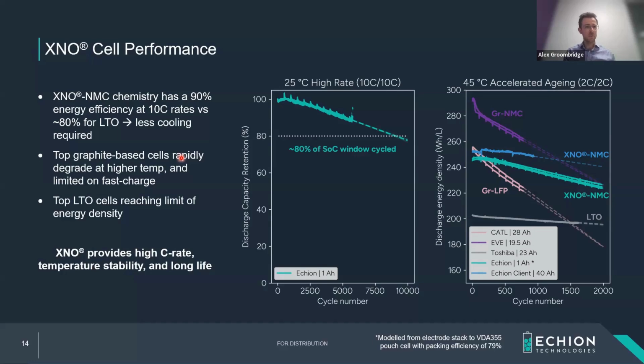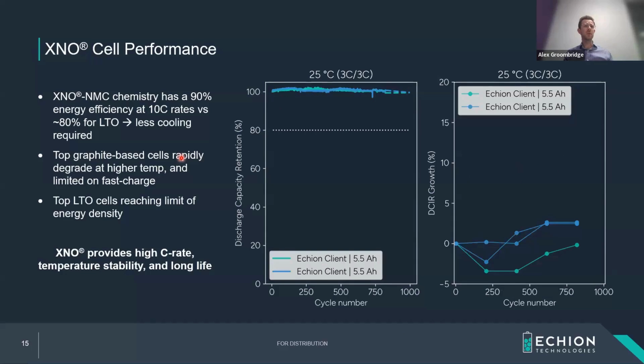I have another couple of examples of some other clients of ours for more room temperature operation. So looking at 25 degrees, 3C symmetric cycling, and you can see these cycle very stably without any real resistance growth from the system. And this resistance growth is an additional very important parameter because when we deal with high C rate applications, there's a square in there somewhere about current and resistance and heat. So you really want to avoid any resistance growth that you can get, because then you need to oversize your cooling system along the way.